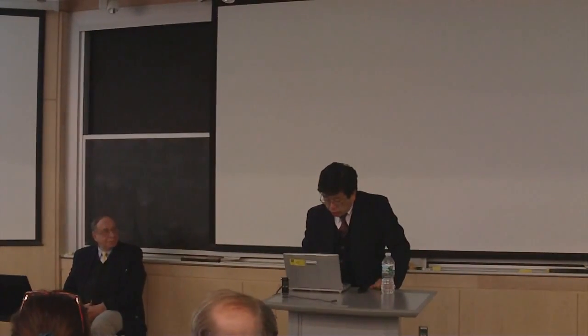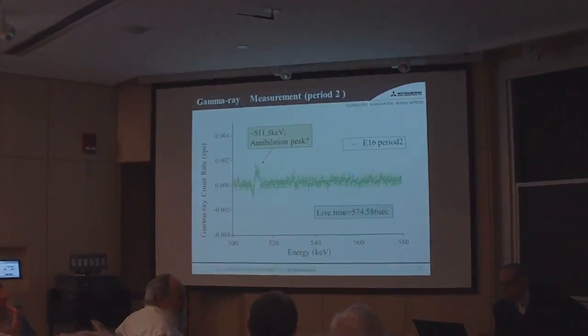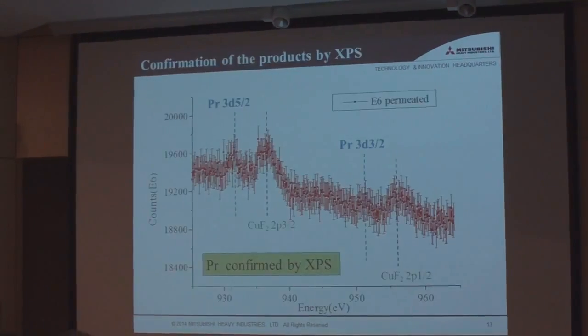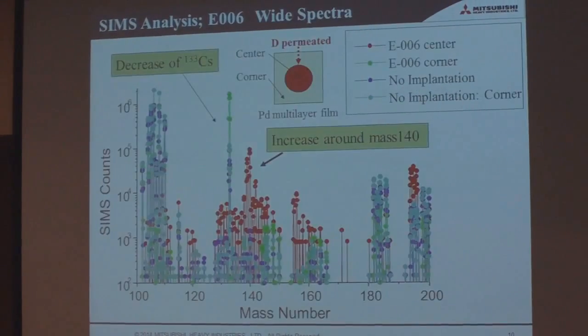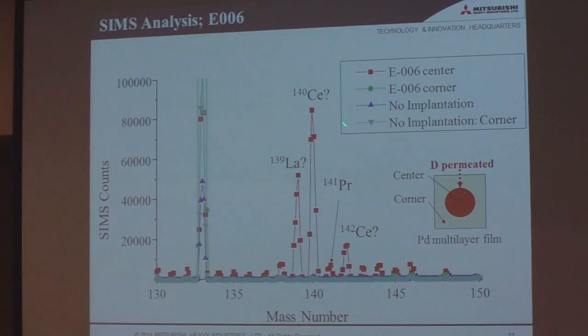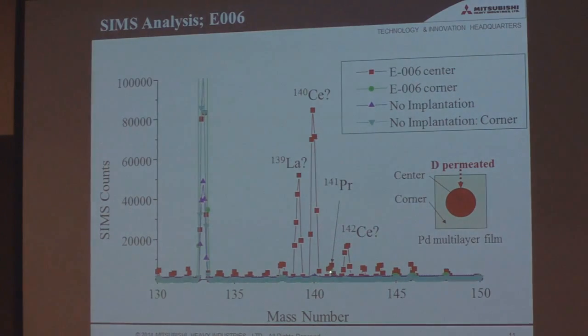I believe you said something about the transmutation being different depending on whether you start with D2 gas or D2O. Slightly different, yeah. In the gas experiment, in the case of cesium transmutation, we get the praseodymium only like this. But in the electrolyte experiment, the praseodymium is not so large, but we also have cerium or lanthanum around here. So in the case of electrolyte, it is not so clean compared to gas. So maybe hydrogen or other impurities play some role, I presume.